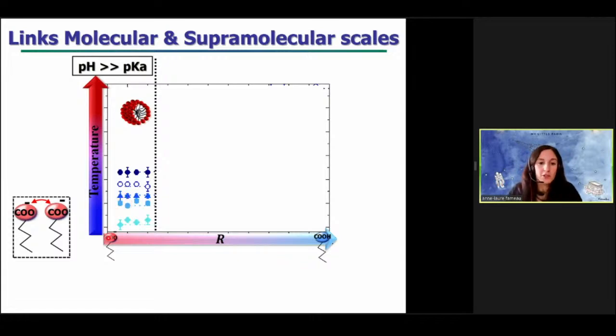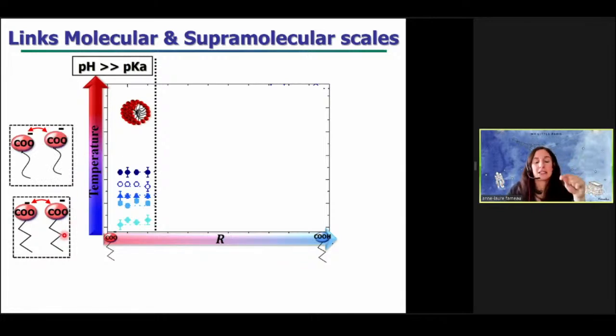And the conclusion is that at low molar ratio, you have an excess of counterion. So the pH is markedly above the pKa of your fatty acid. So all the fatty acids are in an ionized state. At low temperature, the alkyl chains are in a gel state. So you observe the formation of tubes. But when you increase the temperature, the alkyl chains transit from the gel state to the fluid state. And so you have a change to a lower packing parameter and higher curvatures. That is why you obtain the formation of these nanometric size micelles.